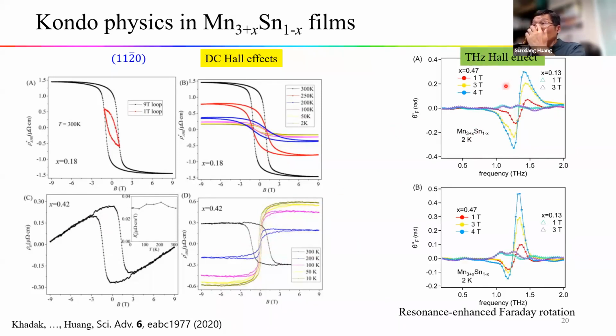So why do we have something like this? We also did this terahertz Hall effect measurement, that is the terahertz Faraday rotation. The idea is that the polarization angle of light will tilt when the polarized light passes through some magnetic materials. So this basically measures the terahertz Hall effect. If we look at a low doped one, the Faraday rotation, real part and imaginary part, is very small and weakly depends on the magnetic field.